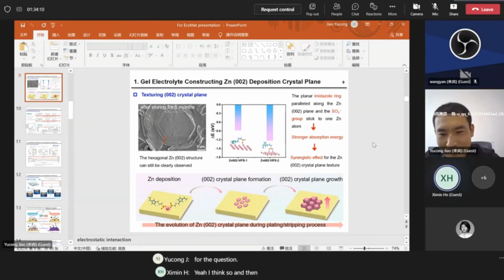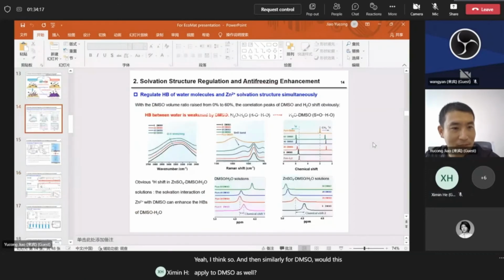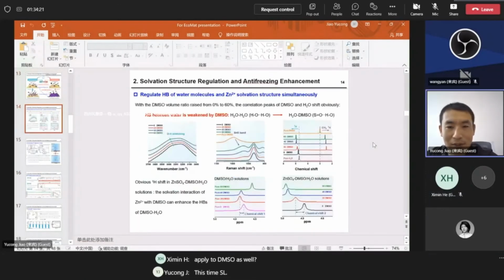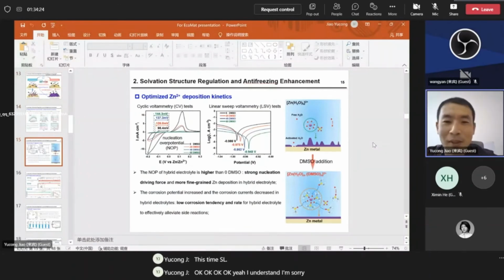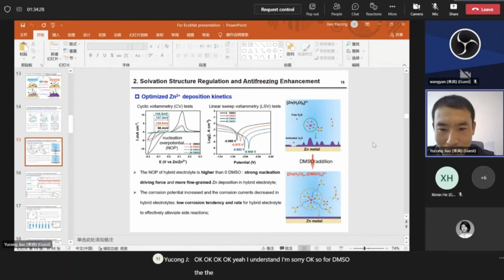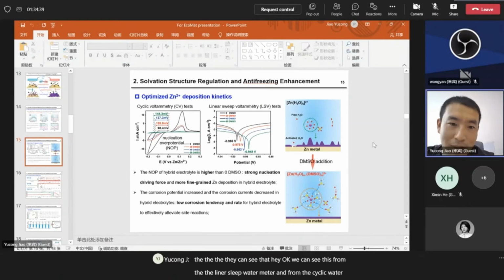Yeah, I think so. And then similarly for DMSO, would this apply to DMSO as well? Okay, I understand. For DMSO, we can see this from the linear sweep voltammetry and from the cyclic voltammetry test. For the CV test, we can see that the nucleation overpotential is much higher with more DMSO. Thereby the zinc deposition morphology could be more fine-grained, and yes, it's more difficult for the zinc ion to nucleate, to deposit with DMSO.